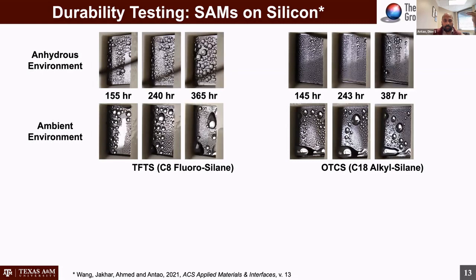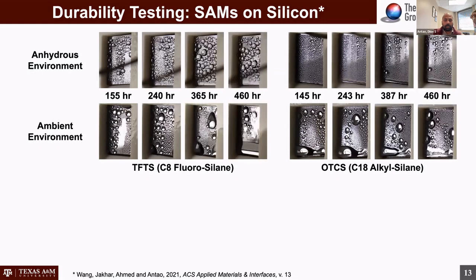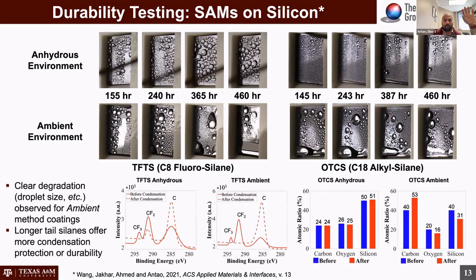But as we progress through the experiment and we get to this point of about 450 plus hours, we start to see that the ambient environment coatings start to fail. And they fail more so on this fluorosilane surface. But if you compare that to the anhydrous environment coating, you'll see little to no degradation on the surface over time, over this entire 450 plus hour testing period.